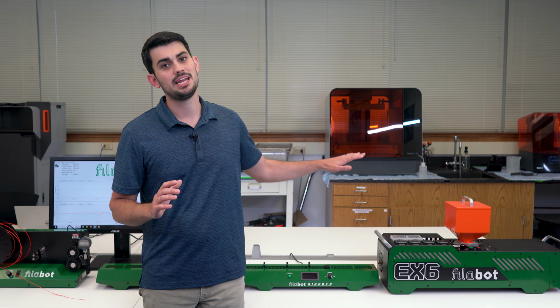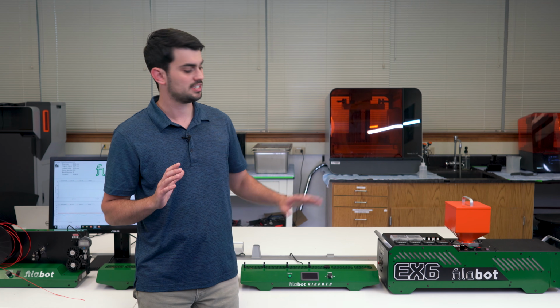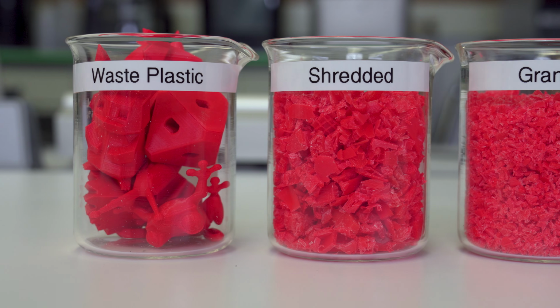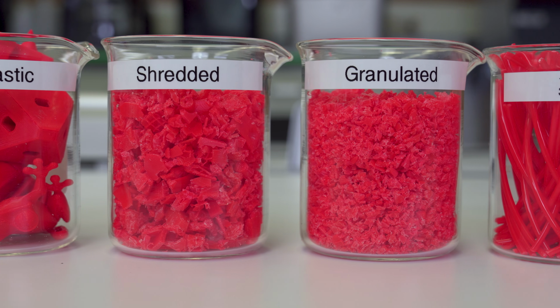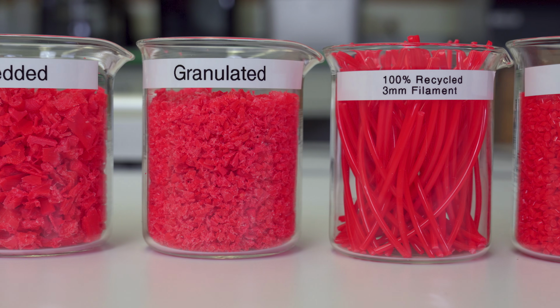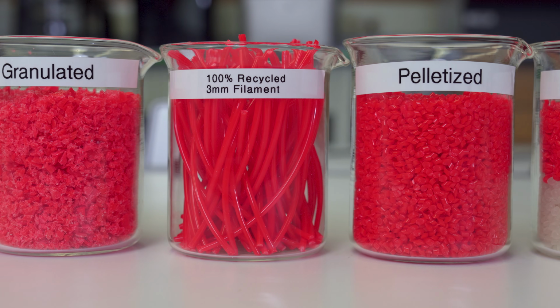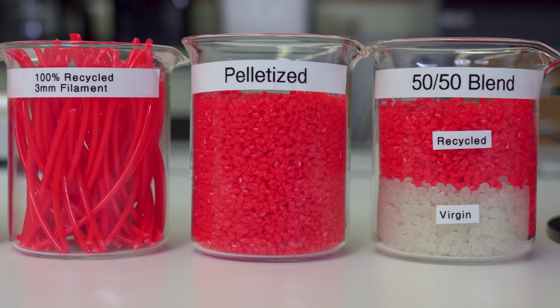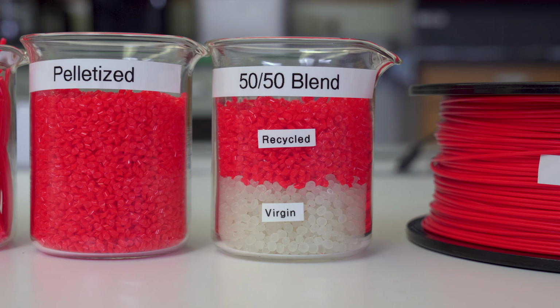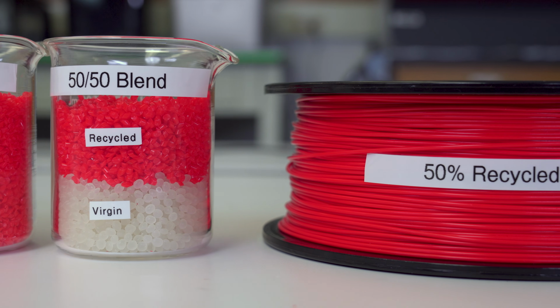So clearly, this setup cannot extrude regrind and pellets simultaneously. This is possible, however, with purpose-built screw extruders that use a special barrel to compress the regrind for more uniform solid conveyance. But it's not possible to switch barrels on the EX6, so what's the solution? Well, this is the part I was talking about in the intro when I said that recycling failed prints is more difficult than you may expect. To get the regrind to have the same bulk density and shape as the pellets, I'm going to have to extrude a 3mm diameter filament of 100% regrind, pelletize it back into 3mm pellets, then mix the recycled pellets with virgin pellets, and then extrude again to make the final filament.